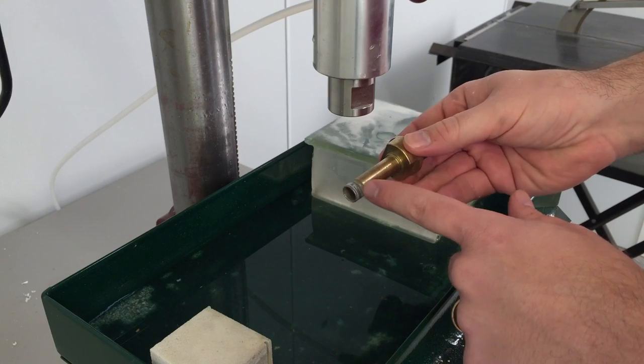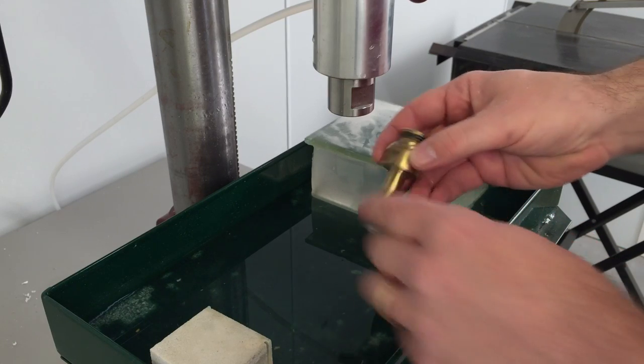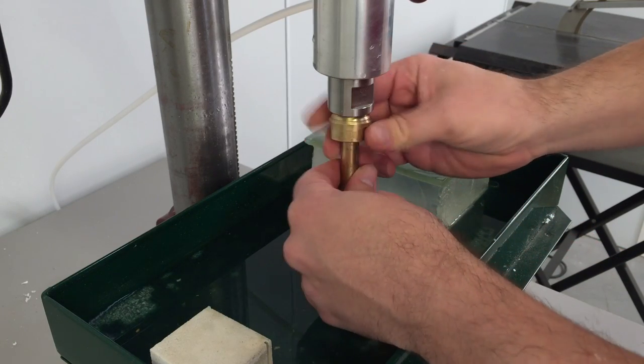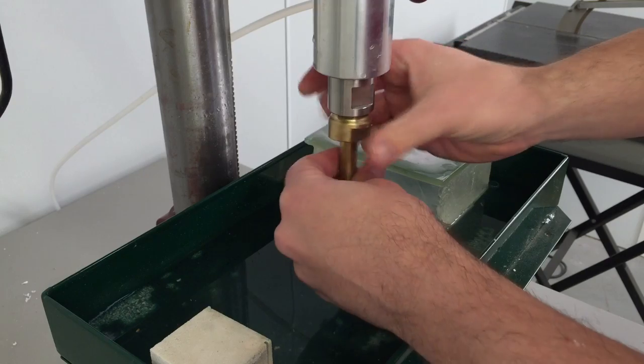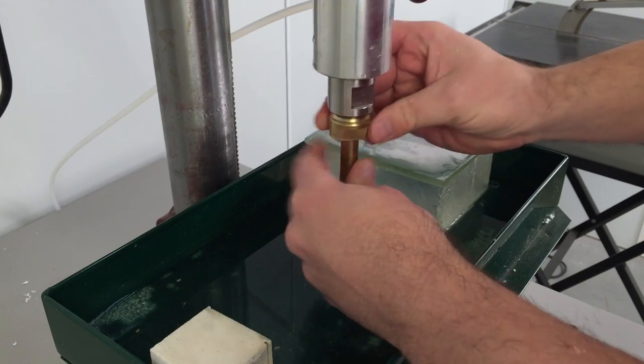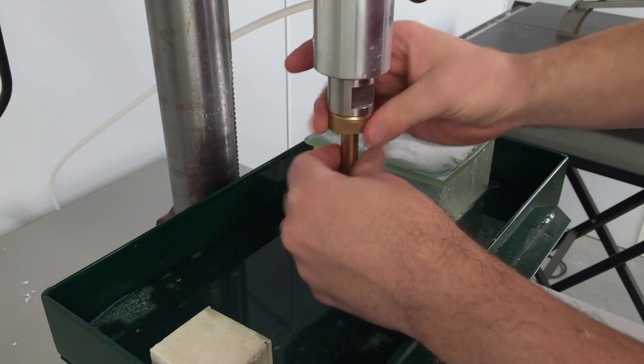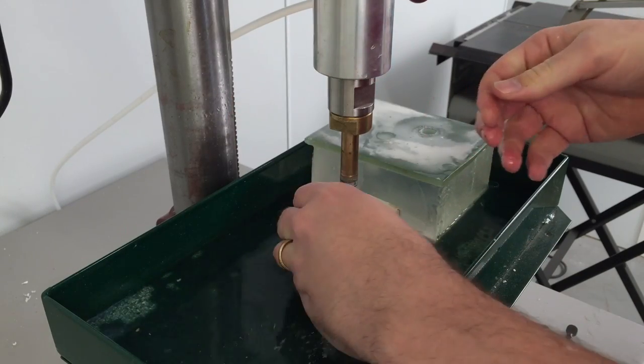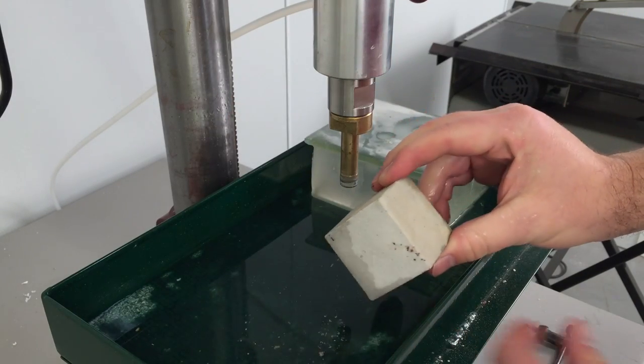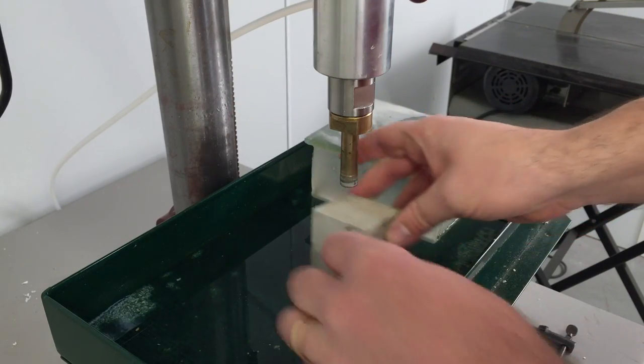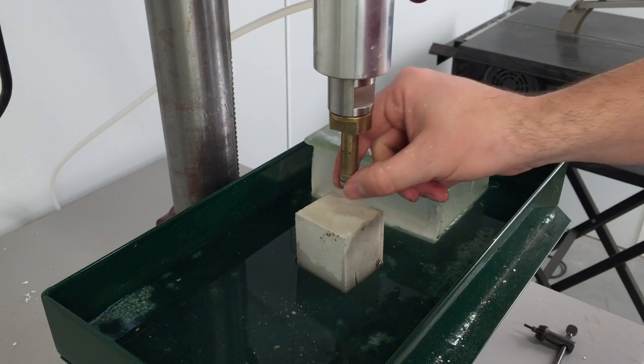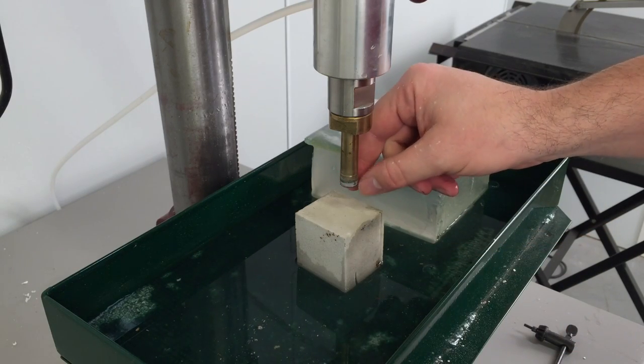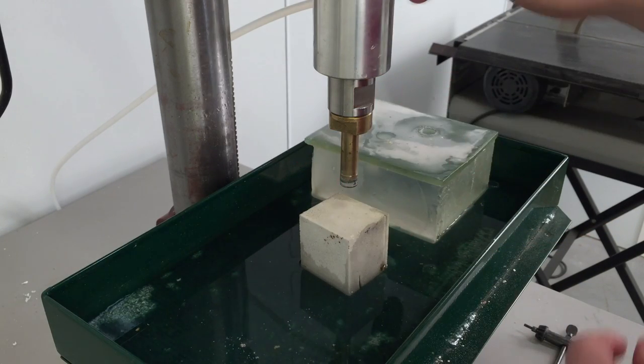Now since my core drill did overheat and I've got some glass that's built up on the core drill itself, I'm going to mount this back into my drill head assembly. I'm going to dress the drill. Now this is a block of our aluminum oxide dressing stick.